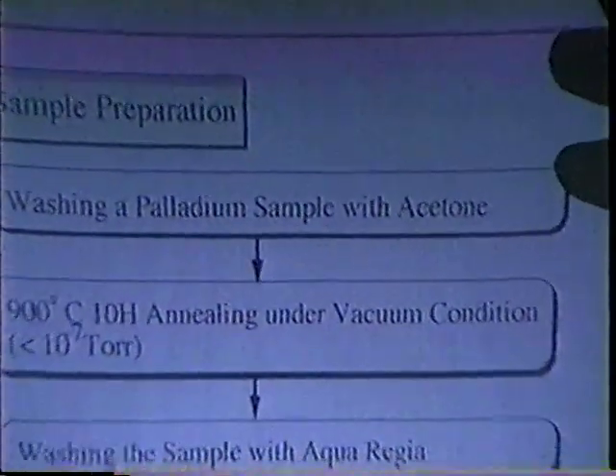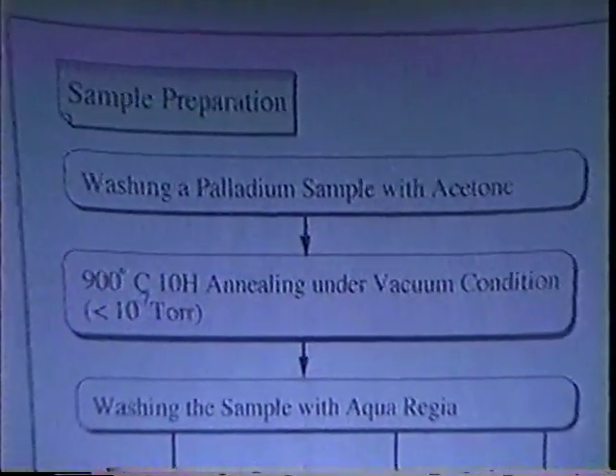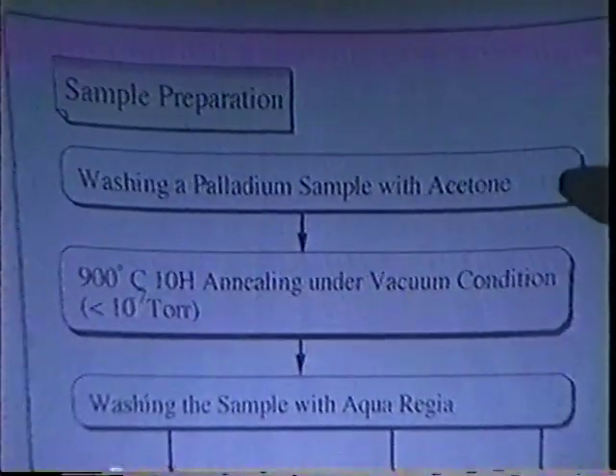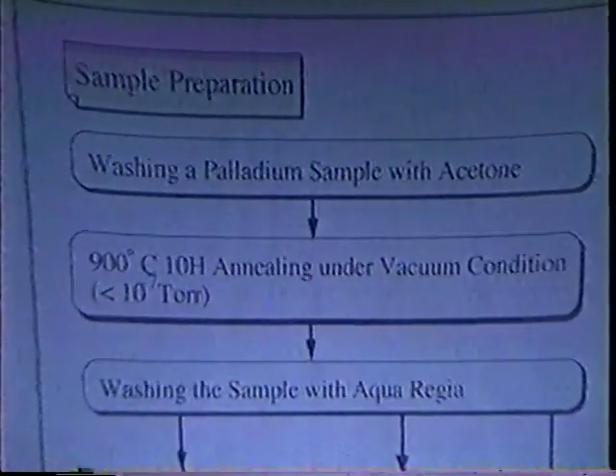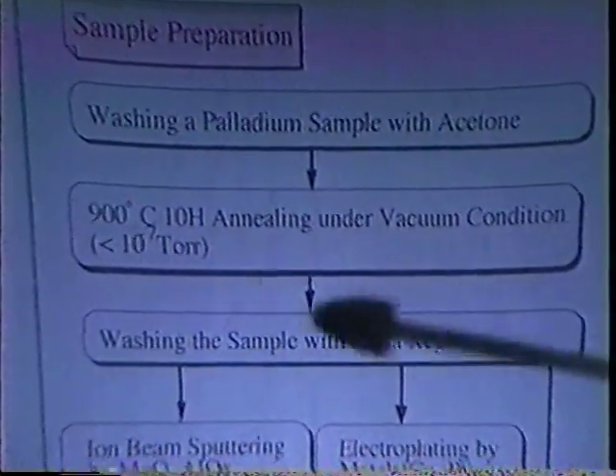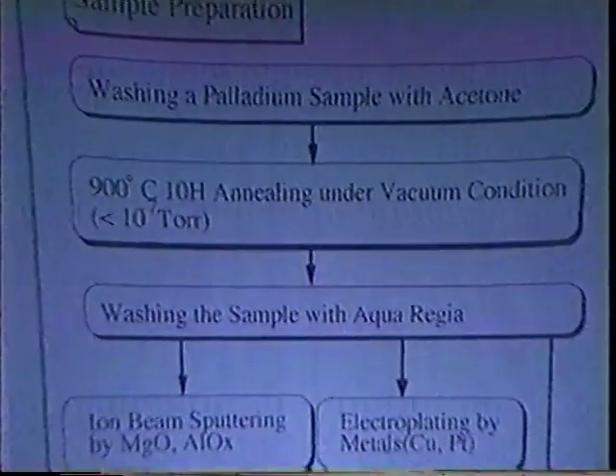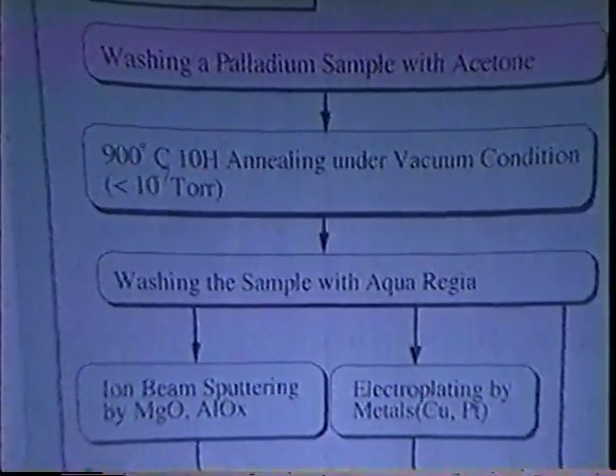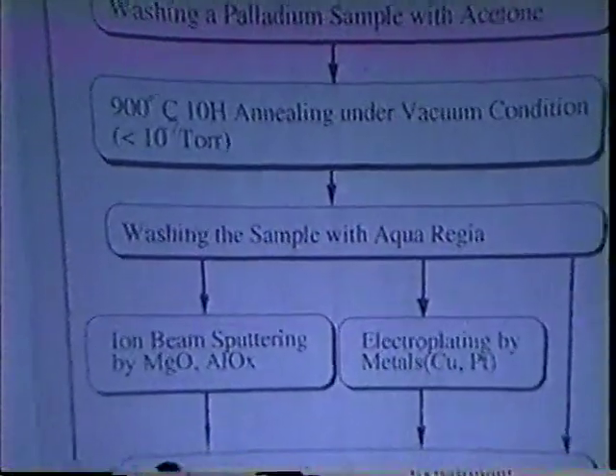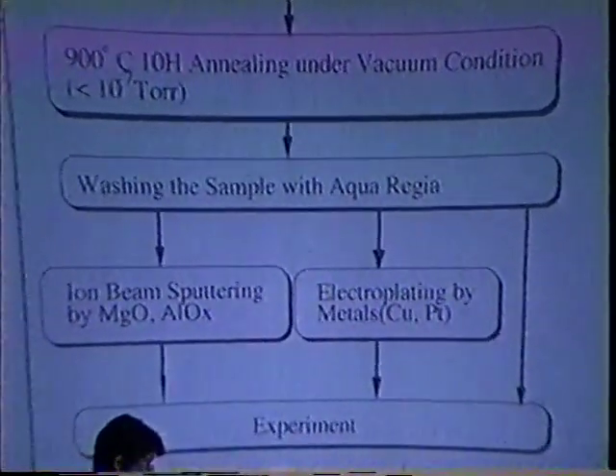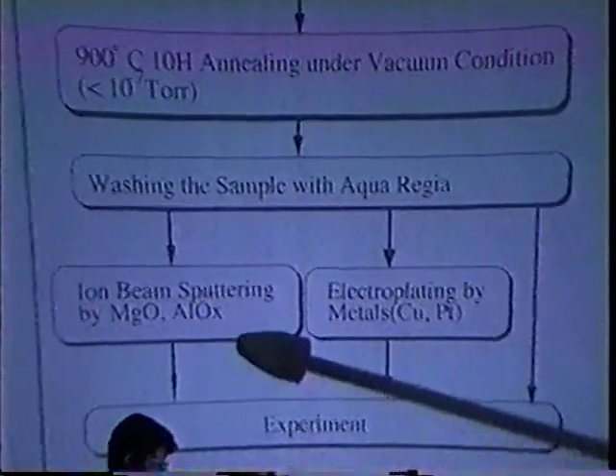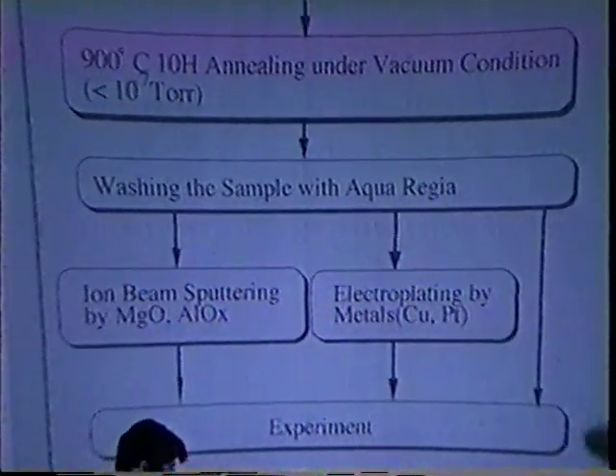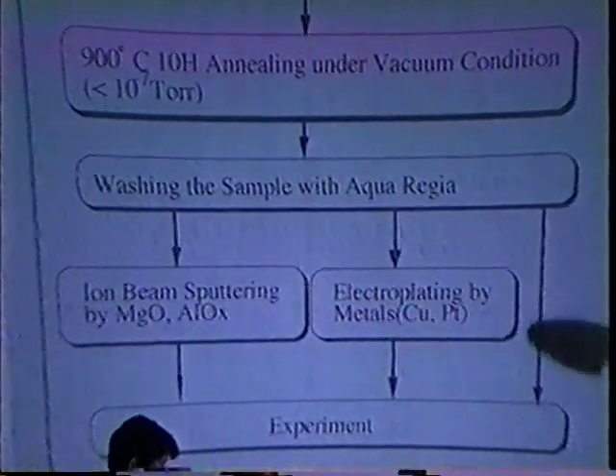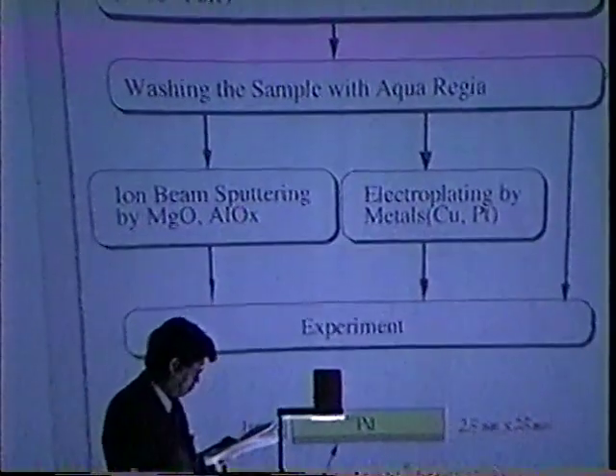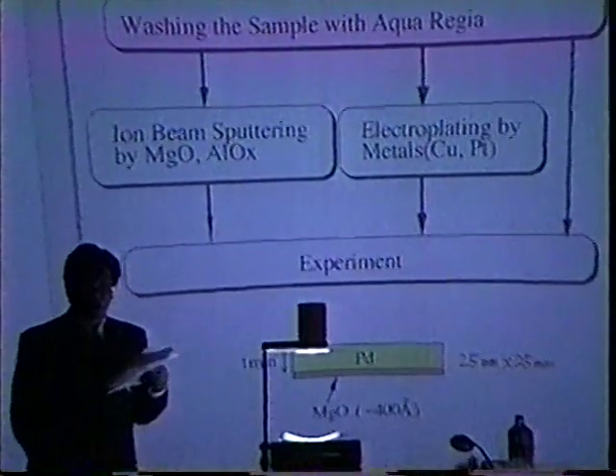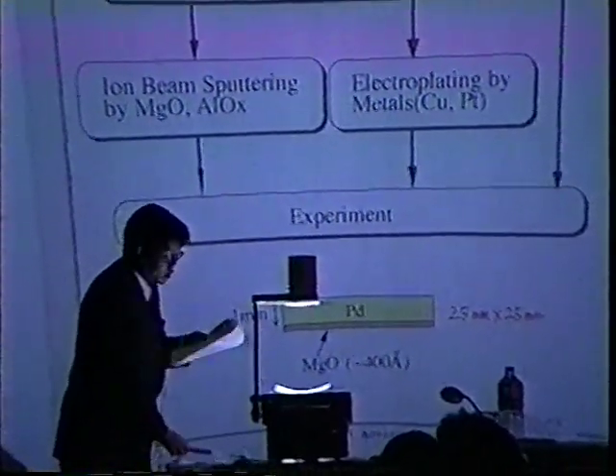Here is a process chart of sample preparation. At first, we wash a palladium sample with acetone. After that, we anneal the sample at 900 degrees centigrade for 10 hours under high vacuum conditions, and wash the sample with aqua regia. After that, some samples are ion sputtered by MgO or aluminum oxide, and some samples are electroplated by copper or platinum, and the others have no films. The size of the palladium is 25 millimeter by 25 millimeter, and the thickness is 1 millimeter.